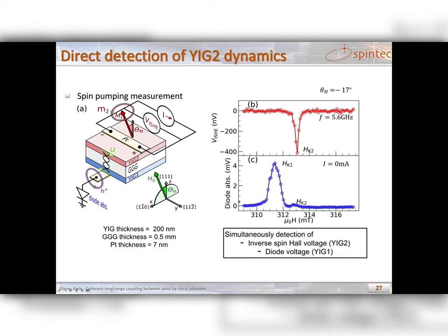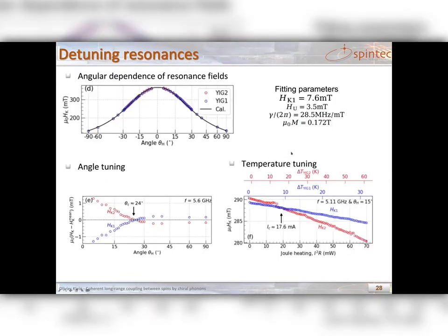And what you can see here is the diode absorption, where you see two peaks, the main peak being the dynamic signal of a layer closely in vicinity with the microwave antenna, therefore the bottom layer, and a small peak due to the top layer. While if you look at the absorption of the ISHE, you clearly see the top layer system. So what we can do now in this system is we can either change the magnetic field orientation to make them cross, or we can apply a current to the platinum to induce Joule heating, which changes the temperature.